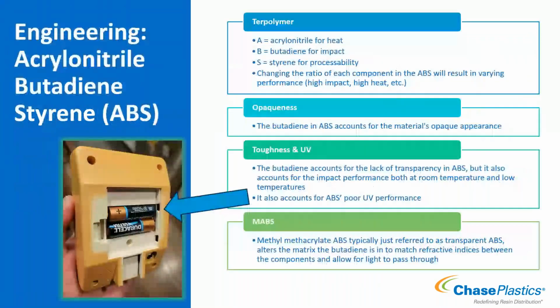Okay. All right, so as you'll notice, as we get into more complex, more engineered products, there's likely to be a little more information on them because there's a little bit more to know about them. So ABS is what we call a TER polymer, TER being 3. So it's got 3 components, A, B, S. And so as a TER polymer, the A in acrylonitrile helps with its heat performance. There are some other smaller things that it also will help with, but the overall driving change when you increase the acrylonitrile amount is going to be the heat performance. Your butadiene, which is a rubber, is good for impact. The styrene portion helps with the processability of the material.